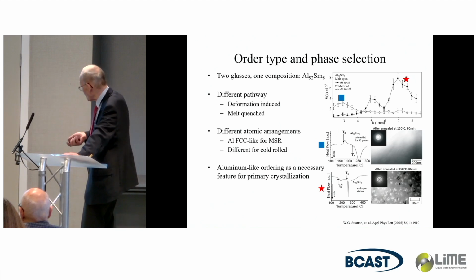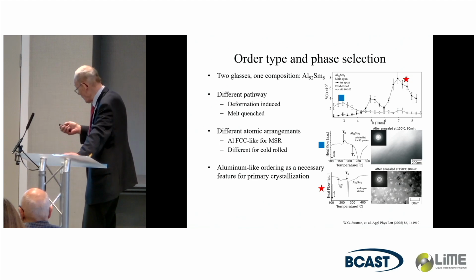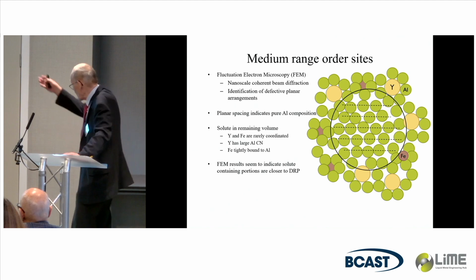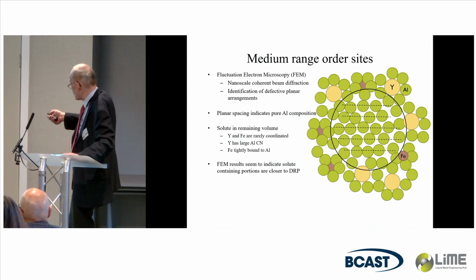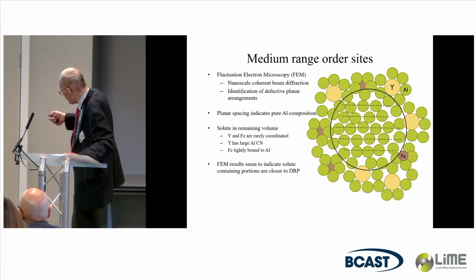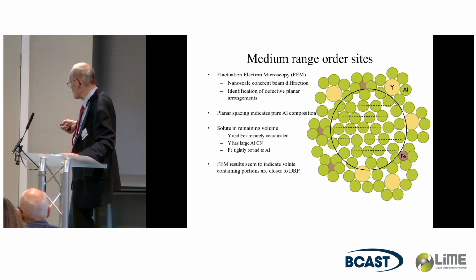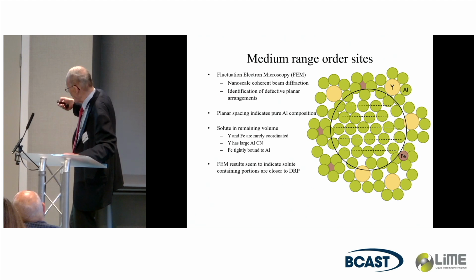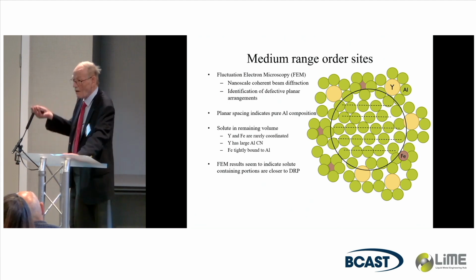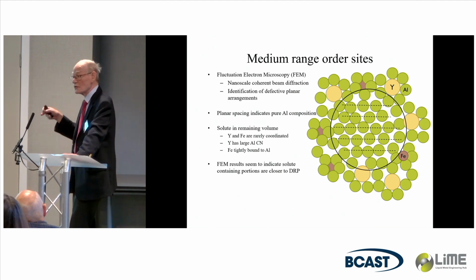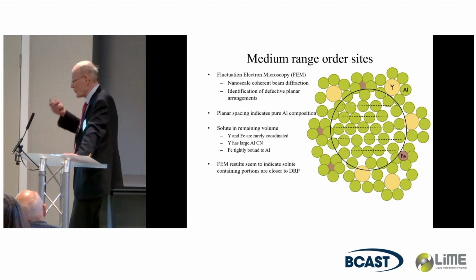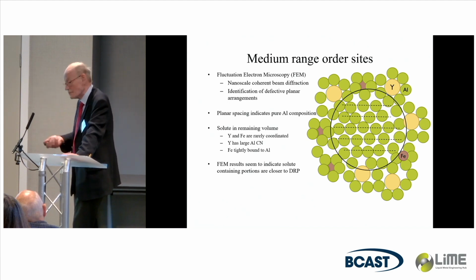And we've done that for these aluminum amorphous alloys after they've been quenched into the glassy state. And it turns out that they're aluminum-rich in their medium-range order. So what that looks like is this. We have an aluminum-rich region which is not crystalline, so we get some constructive interference, but not enough to give diffraction spots. And the solute atoms, iron and yttrium and others, are outside. This is different than what other people have talked about with solute-centered clusters. These are naturally occurring. And it's not surprising since this has more than 88% aluminum, so you would see this.